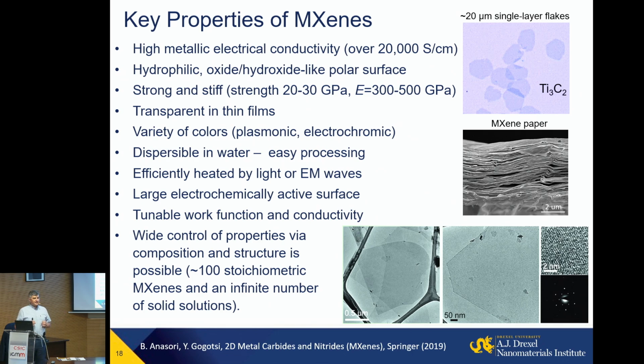But is it useful? If you can get the same properties with clay or graphene oxide or graphene, why really bother? Well, it's still interesting chemistry. But what is important, the key to real application of materials, is of course the property. So what is unusual that MXene bring to the table? One of them is high metallic electrical conductivity. As I mentioned, MXenes are conducting materials. We get, just simply by drying the film, more than 20,000 Siemens per centimeter, pushing to 30,000 nowadays in the lab.